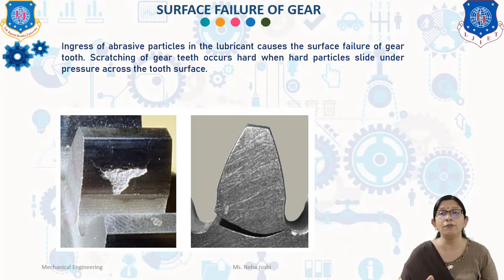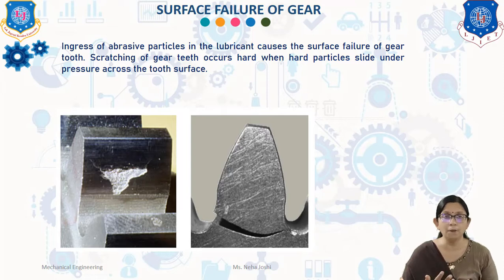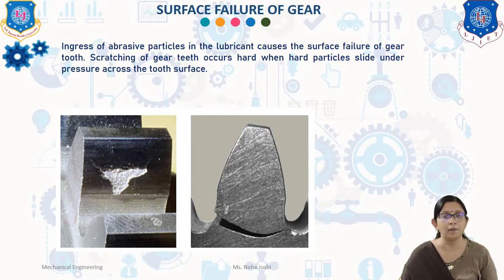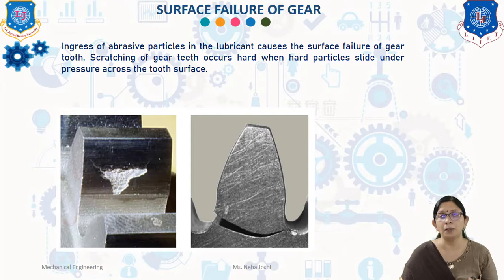One of the surface failures which occurs due to overheating of the tooth mesh joint is scoring. Scoring failure occurs due to the tearing out of small particles that weld together as a result of excessive local heating. After localized welding, the torque being transmitted shears the metal from pinion and gear surfaces and produces irregular surfaces. Such failures initiate microscopically but progress rapidly.